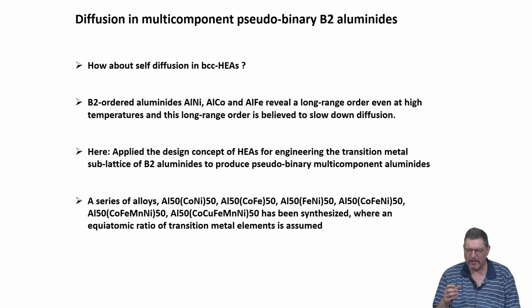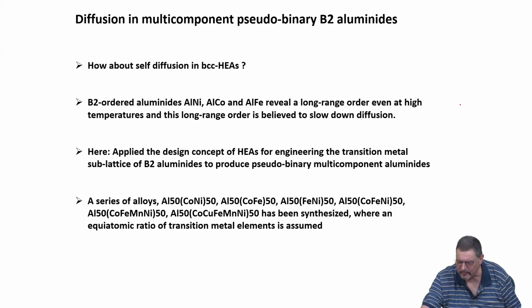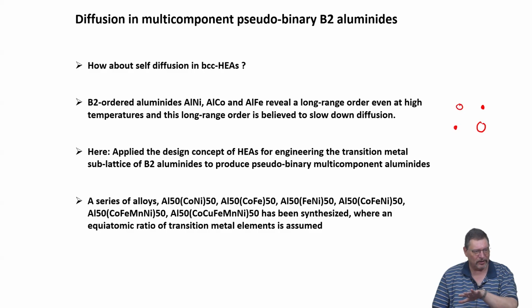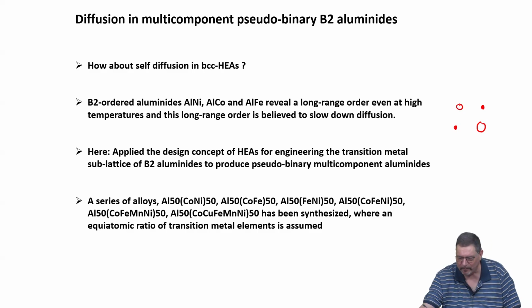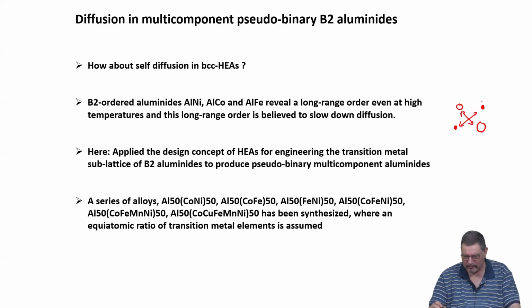Well, because if you have a lattice like this, so let's say this would be an ordered alloy, just a simplified version, the diffusive jump needs to go between here and here and here and here, right? It cannot really go from here to here, because this would destroy the local ordering. So it means this ordering is kind of a selection rule for which diffusive jumps could occur,